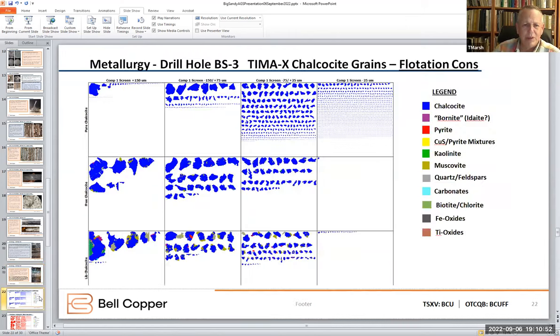Got some TIMA-X images of chalcocite grains. This is the stuff I really love. Electron microscope imaging, really thousands of chalcocite grains for our BS3 sample. So you can see mineral associations and by grinding to minus 100 microns, 80 microns, 40 microns, you get some real nice clean chalcocite grains. And it gives me confidence that with a bit more metallurgical testing, we could make a better concentrate than 25% copper, which isn't bad. I think most smelters today would be real happy to be getting a clean chalcocite 25% concentrate.